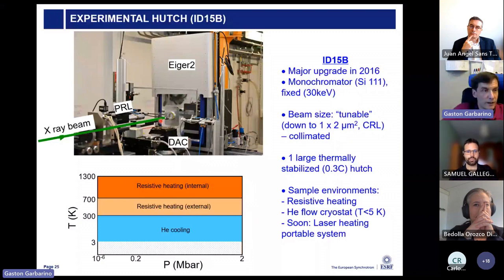On the back, we have a 2-dimensional detector that allows us to collect the diffraction of the sample, and we are able to control pressure and temperature in this range of the pressure-temperature phase diagram, as you can see here. We can couple with resistive heating to reach temperatures of the order of 1300 Kelvin. We can install a helium flow cryostat to cool down to 3 Kelvin, and soon we are developing a laser heating system to be coupled with the beamline. So the idea is what we can do.